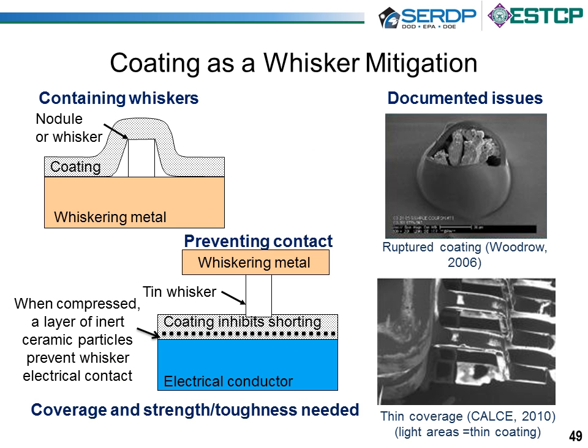So when we look to conformal coating as a whisker mitigation, the key thing we're trying to do is to prevent electrical shorts. And we have two basic ways of doing that. One is containing the whiskers, keeping them trapped on top of the metal, or if we've got some whiskering from an adjacent surface, preventing electrical contact. In this particular project, we're looking at nanoparticles, ceramic particles, to provide additional isolation and coating improvements. And what we really need in the coating is coverage, strength and toughness. Some documented issues you can see up here: ruptured coating from silicone coatings. It was thick, but a nodule grew underneath and ruptured the coating.